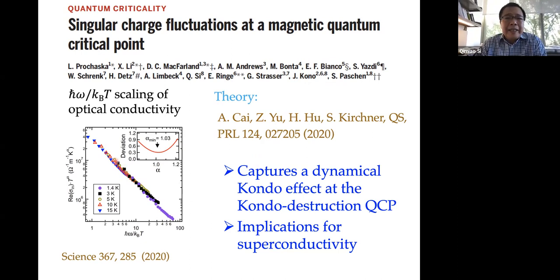Within the frequency and temperature window that can be accessed, one sees that the optical conductivity follows this h bar omega over k_B T scaling. And so we interpret this as saying that the quantum criticality, even though it's a magnetic quantum critical point, the charge degrees of freedom are also involved. And that's precisely what one would expect based on this additional critical modes associated with the destruction of the Kondo effect.